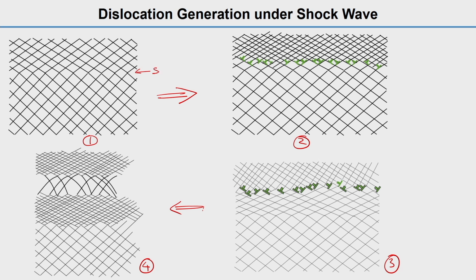This is the shock front. So, the shock is coming from this way, this is the front. You can see that this is the compressed region, and here it is uncompressed. Similarly, in the second stage, this is uncompressed, this is the compressed region, but in stage 2, what is happening here is that some dislocations are generated.